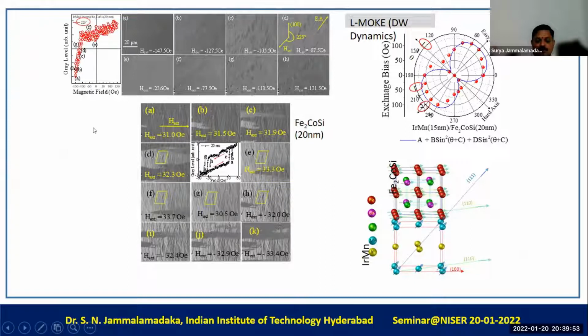So then, to confirm whether there exists an exchange bias or not, we also did the magneto-optical Kerr effect studies. We do see a shift of the magnetization loop from the magneto-optical Kerr effect. We also looked at the direction of the magnetic domains that we obtained. The direction of the magnetic domain is along the